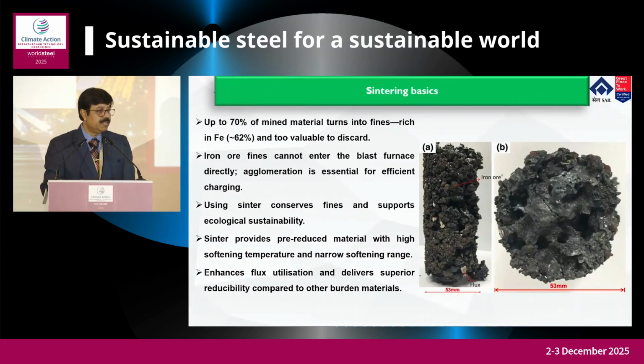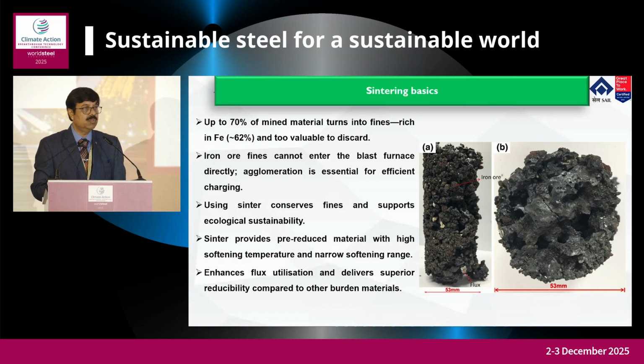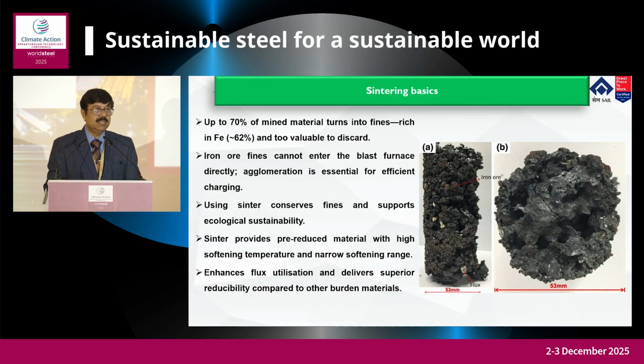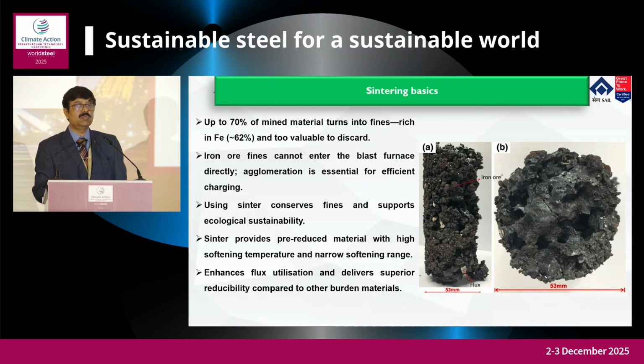Now this is sintering basics and coke breeze. What is sinter? The iron ore fines are basically most of the fines generated by the mining of lump ore, and those fines cannot be rejected. We used to charge fines into the blast furnace, but as fines they cannot be used there. So we agglomerate them to form lumps and charge those into the blast furnace.